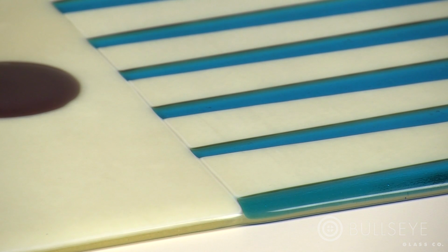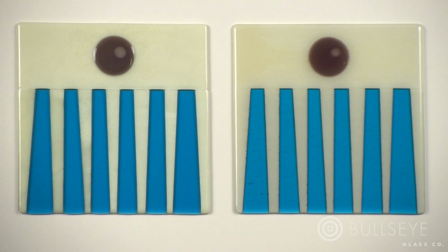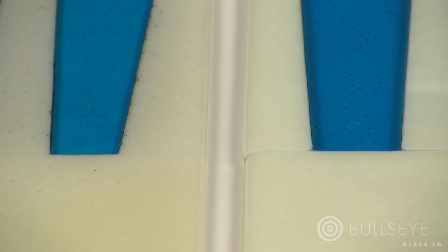Lines between colors in the finished piece will be soft and irregular because some glass colors flow sooner and/or farther than others. Also, the unconstrained seams in the design may pull apart to reveal the base glass. When viewed at a distance, design up and design down tiles may seem quite similar, but seen up close, there is a world of difference.